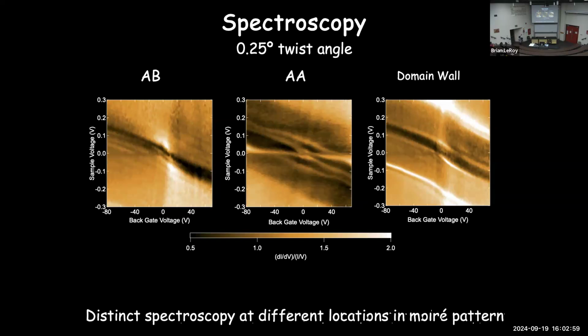And what I'm doing is I'm probing as a function of energy in the y-axis, and the x-axis is the electric field that I'm applying to the sample. So let me maybe start with this AB stacked region. If I have zero electric field, I have basically fairly uniform density of states. As I apply a larger and larger field here, I get this region of black showing up here. That means I'm opening up a band gap in the sample. There's a region where we have no states available for tunneling. That's the band gap in the material. And so that's where it's gapped. In the AA site, okay, there's kind of a bunch of crazy lines going different ways here.